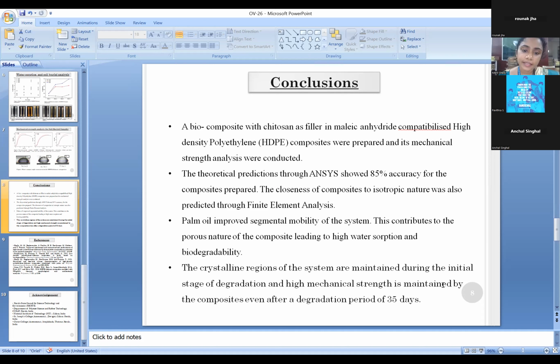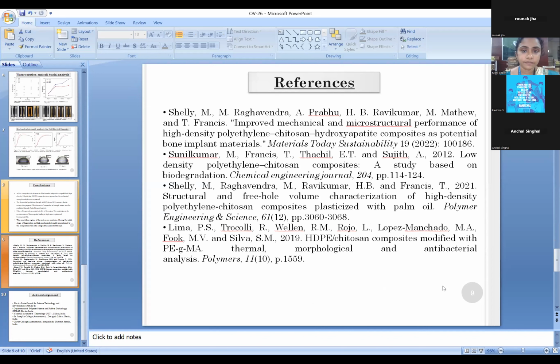The palm oil has increased the segmental mobility of the system. With the increase in the concentration of palm oil, the segments could easily move, so that better interaction between the filler and the matrix was observed. And also it has led to the formation of a highly porous composite, leading to high water absorption and better biodegradability. The crystalline regions of the systems were maintained during the initial stage of degradation, and high mechanical strength was maintained by the composite even after a degradation period of 35 days.